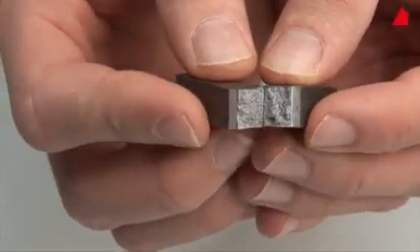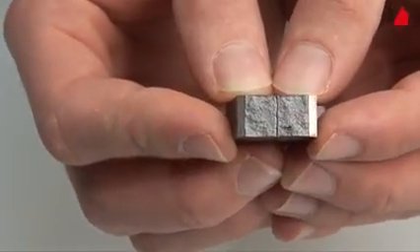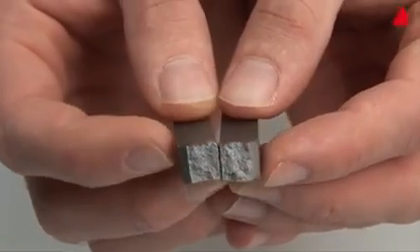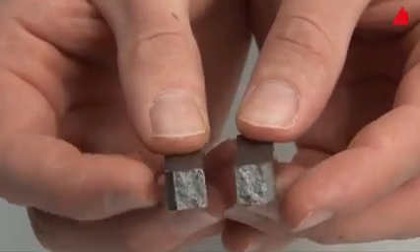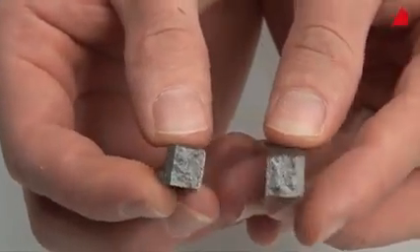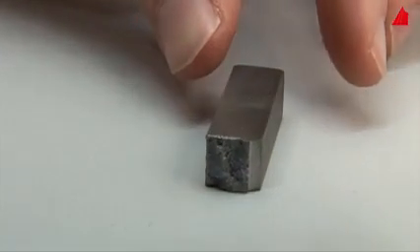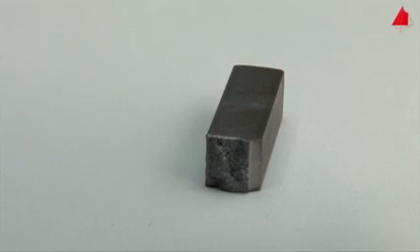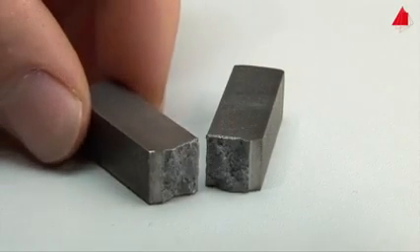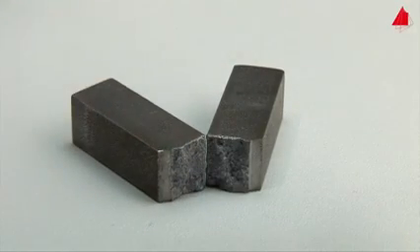The first specimen only shows very little plastic deformation. A mostly flat, slightly glittering fracture surface has been formed. This is another important indication that this kind of steel is only able to absorb small amounts of notch impact energy. It shows mainly brittle behaviour due to the strain ageing effect.